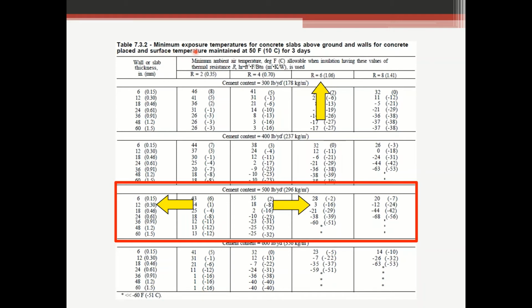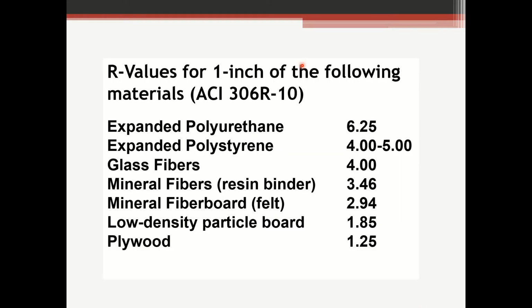There's multiple tables. This particular one is for concrete slabs above ground and walls. There's a different one for slabs on grade, and I think there's a third one as well. But this one seemed most appropriate, so I showed you this one. So this R value of 6. Let's keep that in mind. How do we get to an R value of 6? 306 has different R values for different types of material. So this is for 1 inch of expanded polyurethane, with an R value of about 6.25. Expanded polystyrene, 4 to 5, glass fibers, 4, mineral fibers, and so on and so forth. So if you've got 3/4 inch plywood as your formwork, you've got about an R value of 1 right out of the gate.